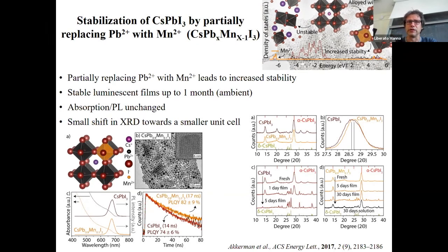Now, maybe the most important thing is that alloying with manganese does not change at all the optical features of the nanocrystals compared to the pure cesium lead iodide nanocrystals. But here you see the very big difference. Standard cesium lead iodide, here indicated as alpha phase cubic, undergoes transition to the non-perovskite phase in just 5 days, whereas the alloyed nanocrystals do not undergo transition even after 1 month. Just a slight fraction is transformed.